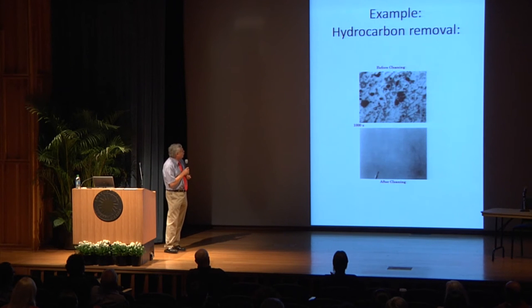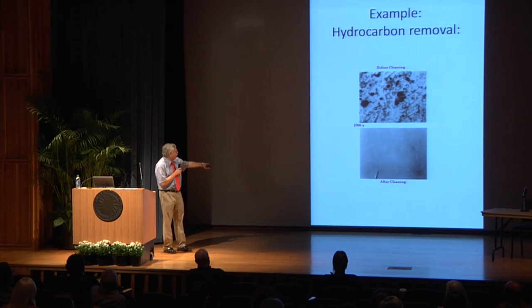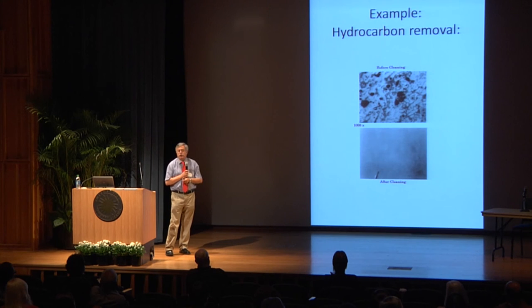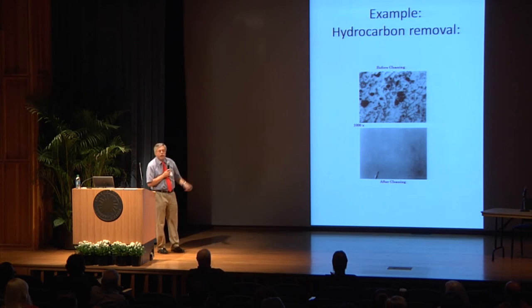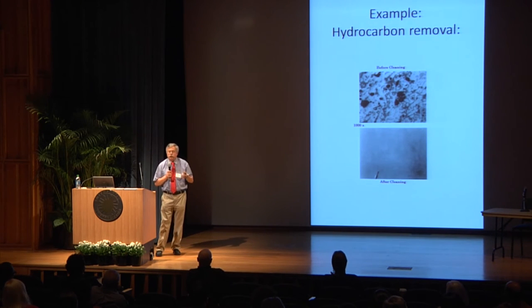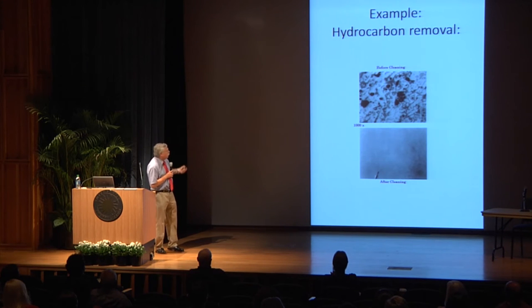Then hydrocarbon removal. There's a crack on a silicon wafer, a scratch. That's the top micrograph, what my facial grease looks like at 1,000x. Not very good. But essentially, we cleaned it. And not only did we image it, we also performed on surfaces what's called XPS to show that not only did we remove all the stain, but we removed some of the background hydrocarbons also. So these basic samples show a lot.